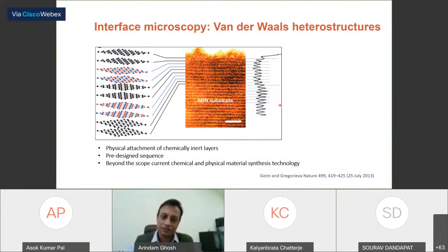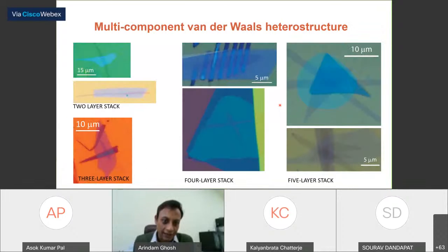For example, if you take a 5-layer structure, these two are essentially graphene layers. This is a 4-layer structure which is encapsulated between 2 layers of boron nitride. It turns out that this is an interesting structure because having boron nitride, which is an insulator, sandwich a layer of graphene can increase the mobility of graphene enormously, because boron nitride gives it a very high quality environment. Okay, you can do a lot of very interesting things, and people have now achieved very high electrical mobility.